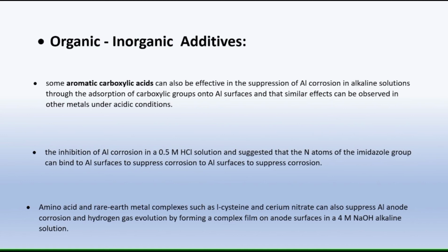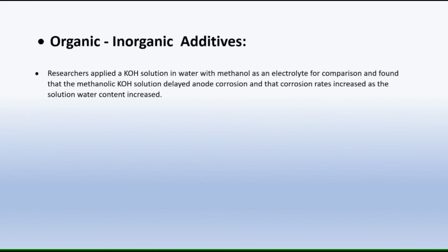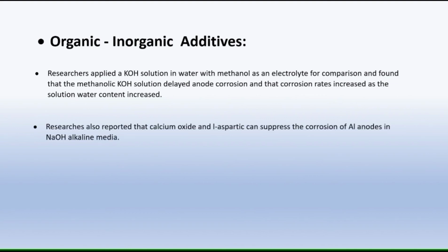Amino acid and rare earth metal complexes such as L-cysteine and cerium nitrate can also suppress aluminum anode corrosion and hydrogen gas evolution by forming a complex film on anode surfaces in a 4 molar NaOH alkaline solution. Researchers applied a KOH solution in water with methanol as an electrolyte for comparison and found that the methanolic KOH solution delayed anode corrosion and that the corrosion rate increased as the solution water content increased. Researchers also reported that calcium oxide and L-aspartic acid can suppress the corrosion of anodes in NaOH alkaline media.